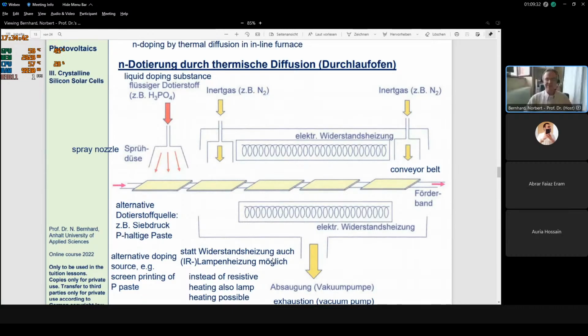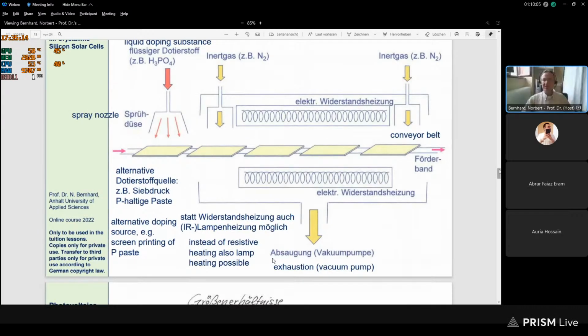Here we have an inert gas curtain just to separate the inner side of the furnace from the outside. And you see here we bring through a spray nozzle the phosphorus to the wafer surface, and usually phosphoric acid is used, but as an alternative, we could also use a phosphorus-containing paste. Then, of course, we would not use a nozzle. Then we would use a squeegee or something to deposit it on the wafer surface. And then it goes through this heated furnace, and the phosphorus diffuses again into the wafers.